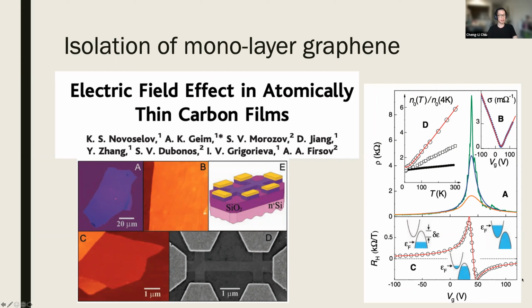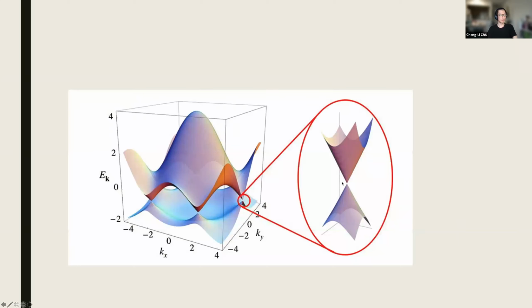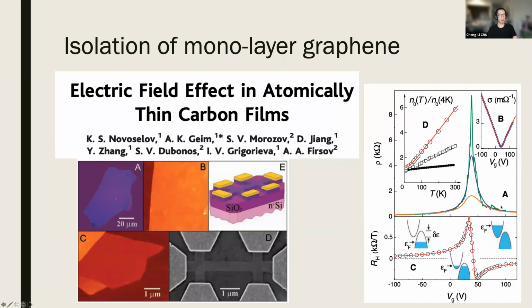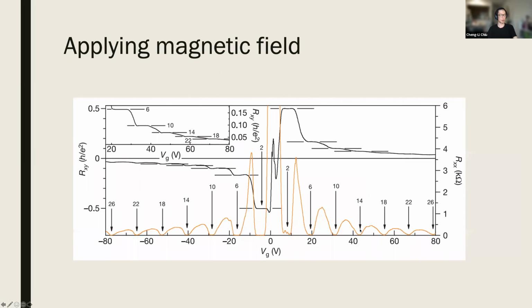So for example, in this figure, the x-axis is the gate voltage. Just like we gate our CMOS transistor, if you gate your graphene, you can change the resistance dramatically. When you are at the Dirac cone, where there's very little electron sitting in this energy level, you have a large resistance, and if you gate it away, you will see the resistance drop. And this turns out to be very easy to get. People have been trying to improve the quality from this, and when you make the quality even better, you see the integer quantum Hall effect as well.